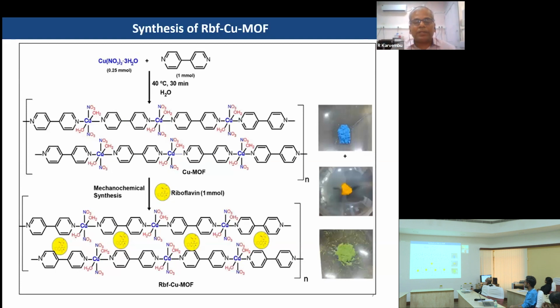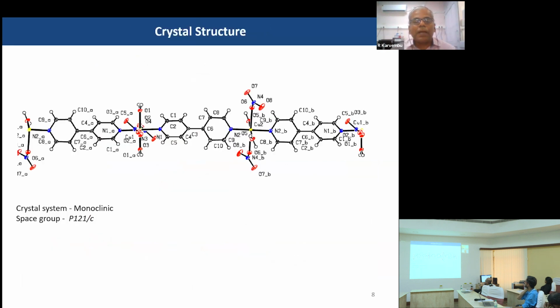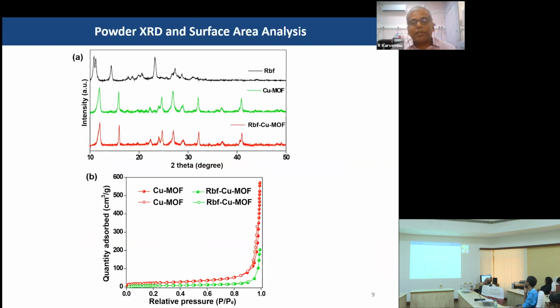After the preparation of this copper MOF, it is modified with riboflavin by means of simple mixing or grinding the MOF and riboflavin. This is a simple mechanochemical synthesis method done using a mortar and pestle. The color of the copper MOF is blue, and once you mix it with riboflavin, the color immediately changes to green.